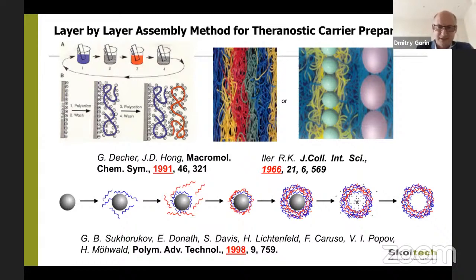The other possibility, you can use, instead of a calcium carbonate core, for example, silica particles, or polystyrene particles. But in this case, you can use an organic solvent like tetrahydrofuran or dimethylformamide for dissolving the core. And in this case, you can freely dissolve the core. It does not dissolve the shell. And you can find many such types of polymer shells and cores.